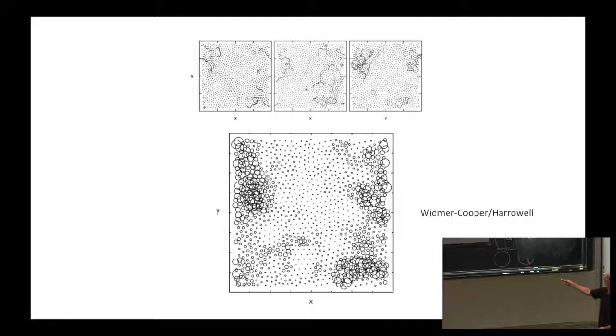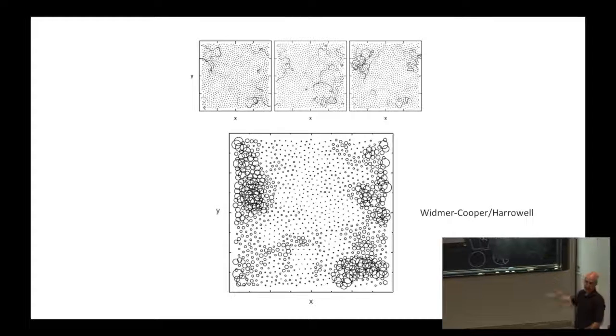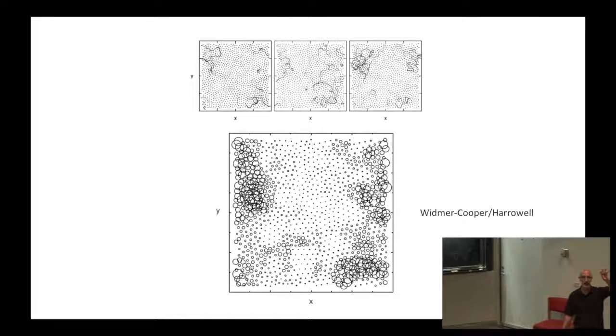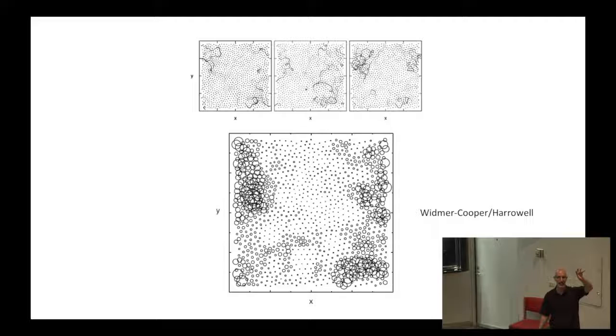So here would be, let's say, 3 different members of trajectories that started from the same initial configuration. And if you did many of these and you put a circle around the particle associated with the size of the displacement that the particle undergoes in some time scale delta t, then a large circle being a large displacement and a small dot being a small displacement, you find that there are regions of higher propensity than other regions.